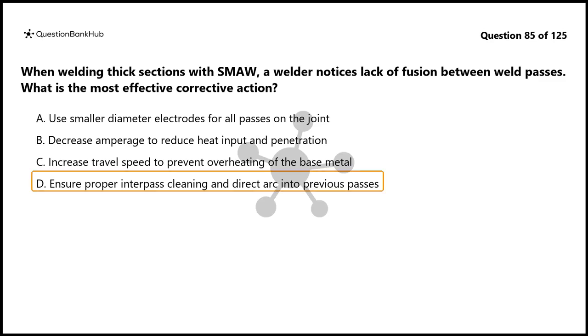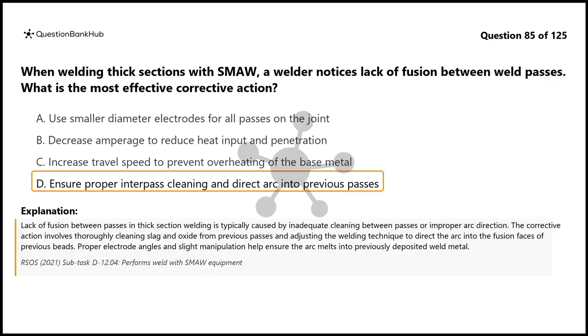The correct answer is D. Ensure proper interpass cleaning and direct arc into previous passes. Lack of fusion between passes in thick section welding is typically caused by inadequate cleaning between passes or improper arc direction. The corrective action involves thoroughly cleaning slag and oxide from previous passes and adjusting the welding technique to direct the arc into the fusion faces of previous beads. Proper electrode angles and slight manipulation help ensure the arc melts into previously deposited weld metal.